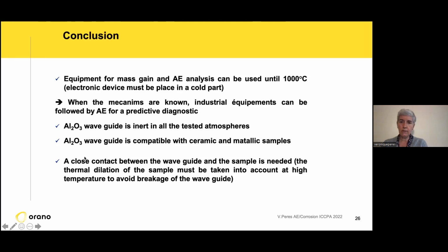And the last point is that you have to have a very good contact between the waveguide and the samples. I did not speak about it, but due to dilatation when we heat the samples, you must be careful about breakage of the waveguide, because if you have a sample with a dilatation bigger than the dilatation of the alumina, it can happen. So this is another limitation of the system.